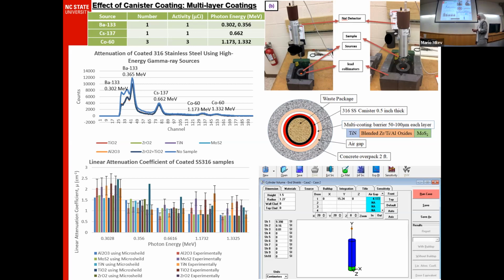We observed fluctuation in the experimental results, unlike the computational ones where they decrease with increasing energy. The experimental values are higher than the computational ones. That can be related to device sensitivity. Environmental effects around can also affect the readings we are taking in the lab.